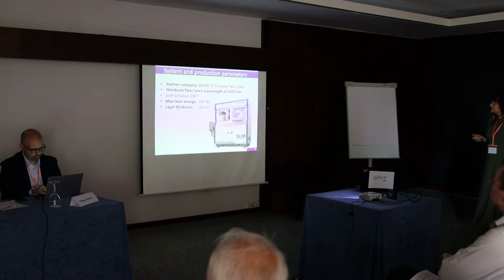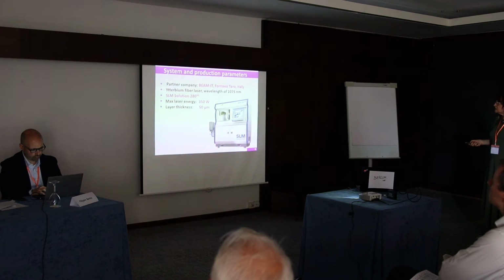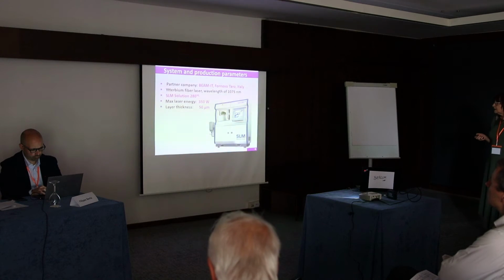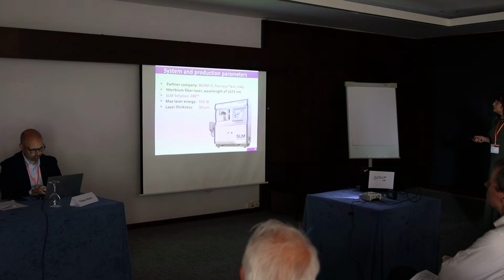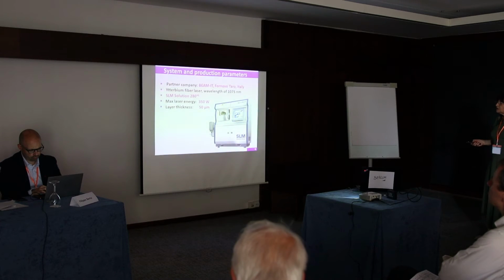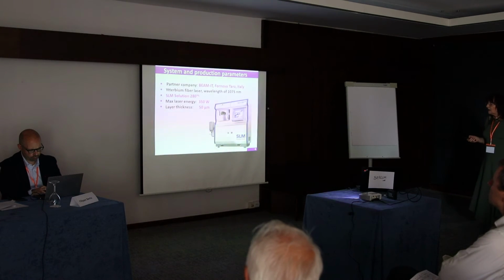Here we can see the system used for fabrication of the specimens. This was an SLM Solutions 280 machine. Specimens were prepared at partner company BEAMIT in Fornovo di Taro in Italy. It uses an ytterbium fiber laser with a wavelength of 1075 nanometers. Maximum laser power was 350 watts, and layer thickness was 50 microns.